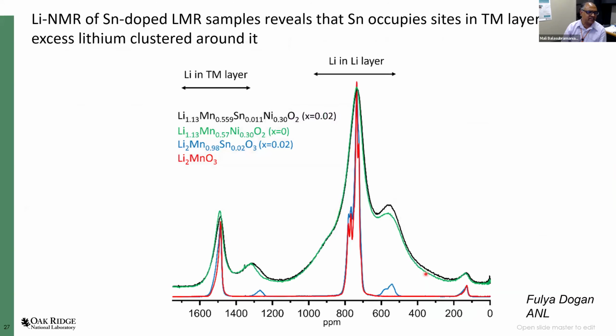So last but not the least, I should show that we also looked at it with NMR. Fulya Dogan, who's an NMR expert, looked at this at Argonne. And again, consistent with the XAFS studies, what we find is that in the doped composite material, there is some extra intensity that can be assigned to environments which look like Li2Mn0.98Sn0.02O3. That is, again, tin occupying manganese type sites, and the excess lithium that is there in this material is also clustered around the tin, which is what we see with X-ray absorption as well.